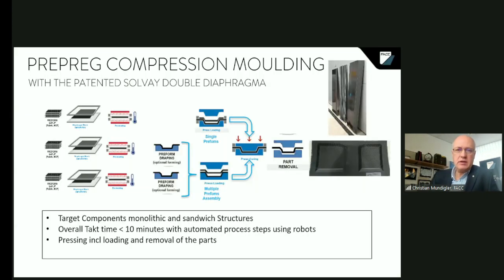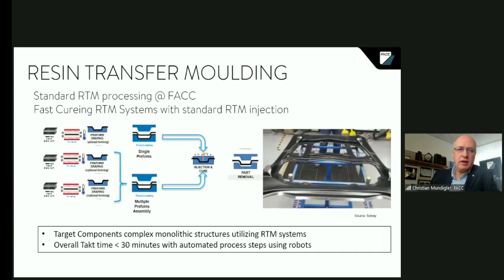So when it comes to thermoset processing, some details: we are using here the Solvay double diaphragm patent. And on the right top corner, you see how a spoiler of a 787 or A350 can look like in the future, produced out of three parts and pressed together in less than 10 minutes, for example. And on the RTM, we are very experienced since many years for the center hinge fittings of those spoilers for the A350 and 787, where we are single source, and using that RTM method, we reduced the weight by 2/3. Here we come to a tack time less than 30 minutes.